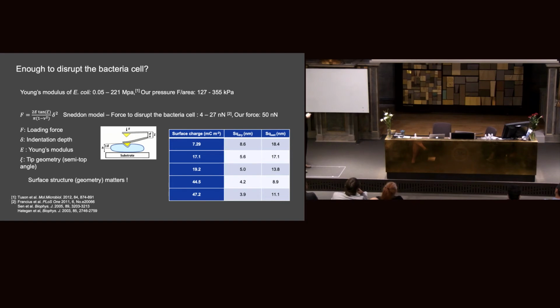Based on studies before, the force to disrupt the cell membrane has been reported from 4 to 27 nanonewton. But this force depends on what kind of tip you are using, so it depends on the tip geometry. There is a correlation between the force required to disrupt the membrane and the tip geometry and also the indentation depths. This is called the Sneddon model.